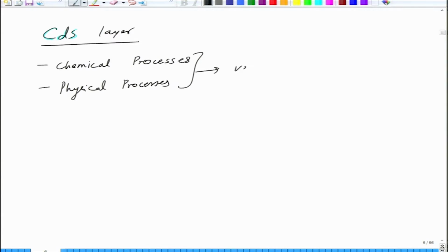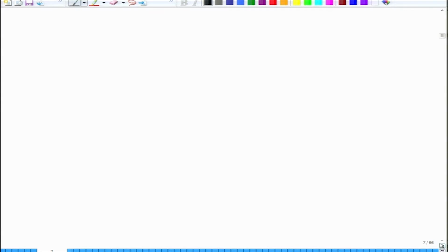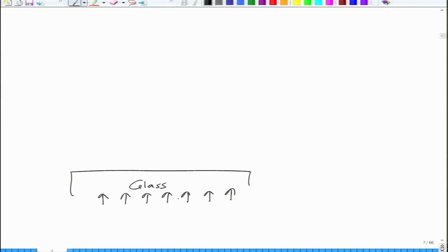And this thin film is very thin. Okay. So the issues which are there in the process, what are the things that one adopts to improve the process? So the device structure that we get is something like this. So we have glass substrate. So this is glass, transparent glass, the light comes from this side, and then we have TCO. TCO means transparent conducting oxide. Then we have a thin high resistance oxide, HR oxide.